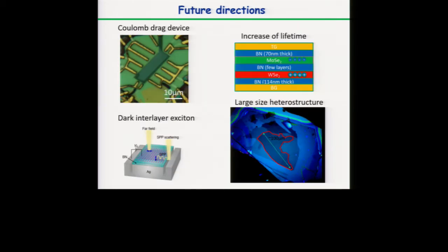Well, now let me go to future directions, mainly for the interlayer exciton part. We can now make a Coulomb drag experiment with interlayer excitons. We can apply current in one layer and measure the voltage in the other layer. So that's the next generation of devices that we have. We can increase the lifetime of the interlayer exciton by placing an insulator in between. That's what we're also working on, by placing boron nitride in between these TMDC materials.